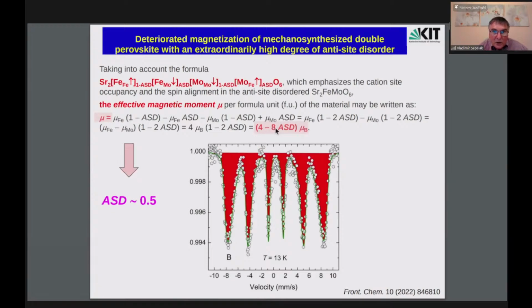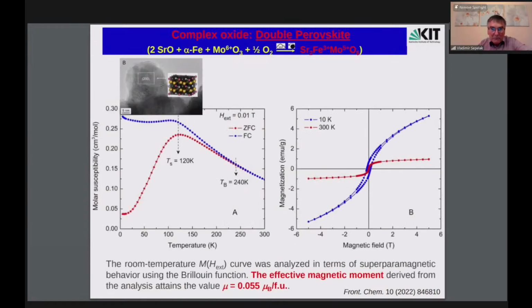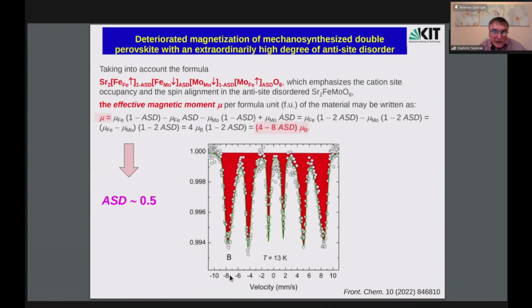And from this, if we put this value of magnetic moment into this relationship, we obtain a high degree of anti-site disorder, almost complete disorder of the double perovskite, where the degree of anti-site disorder of about 0.5 is the maximum value. It was also confirmed by Mössbauer spectroscopy at very low temperature, where we have only one component corresponding to this anti-site occupation of iron on anti-site sites.